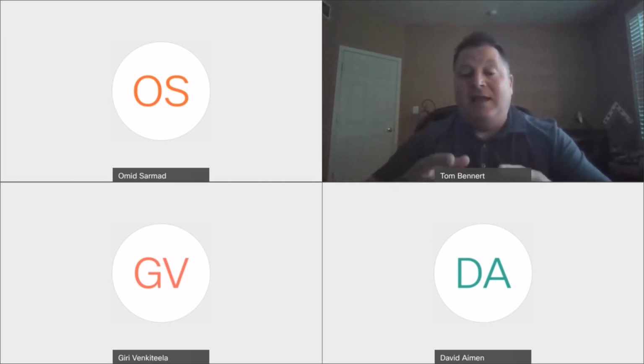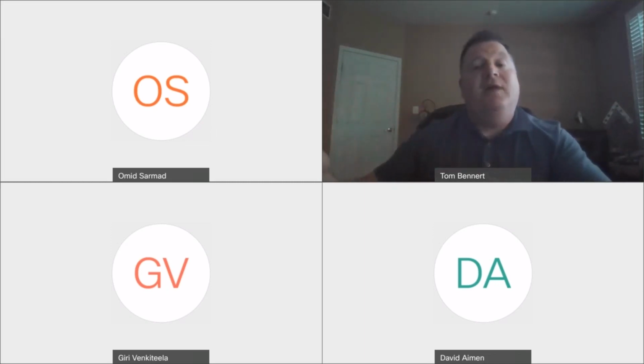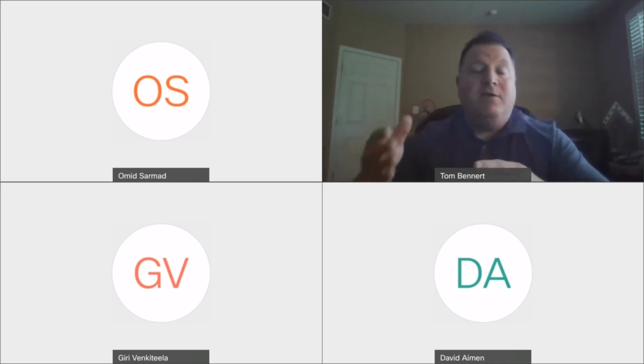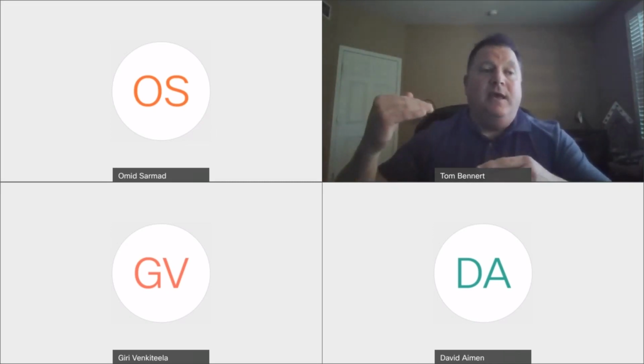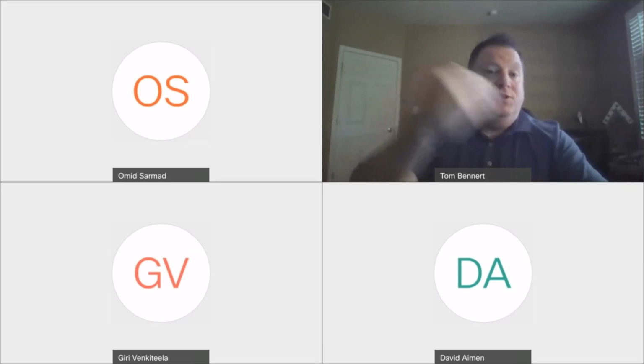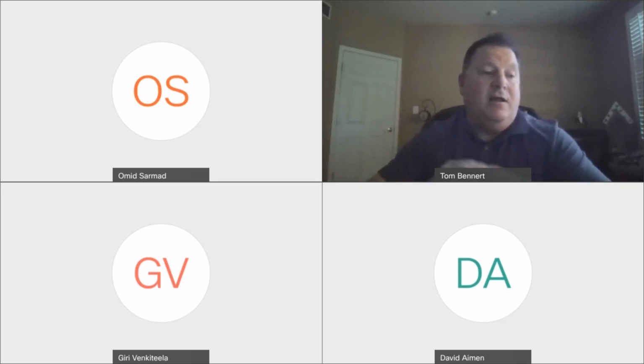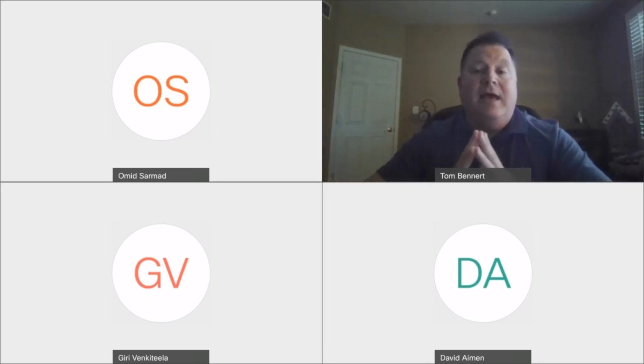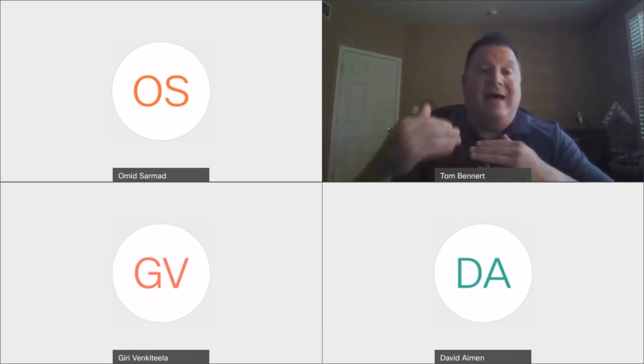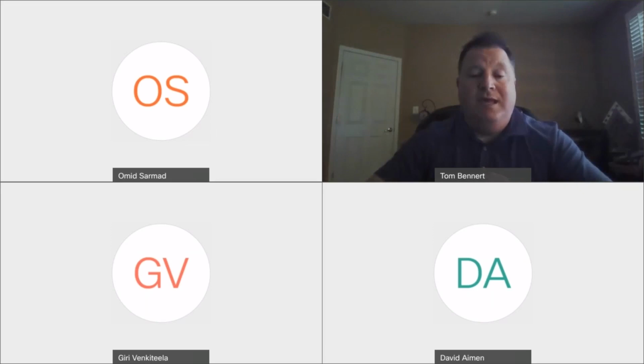I will tell you that HFST also has a certain shelf life. And when that shelf life goes, the aggregates start to pop off and that friction drops down very quickly. We've seen that on a couple of test tracks actually, where that can happen as well. So monitoring that friction is important because obviously you want to catch that before you get to that stage.